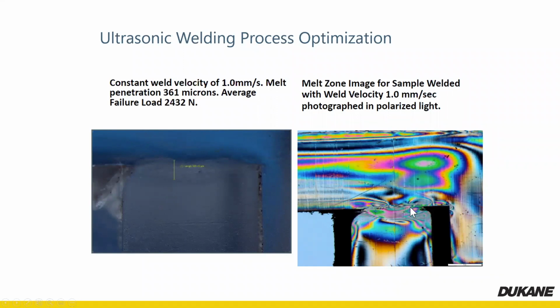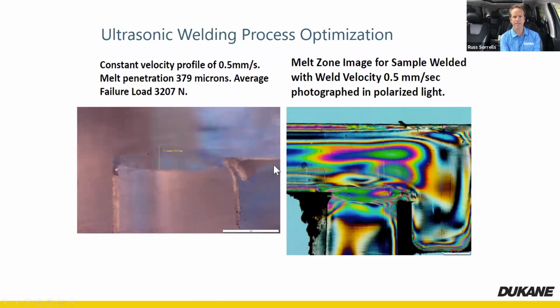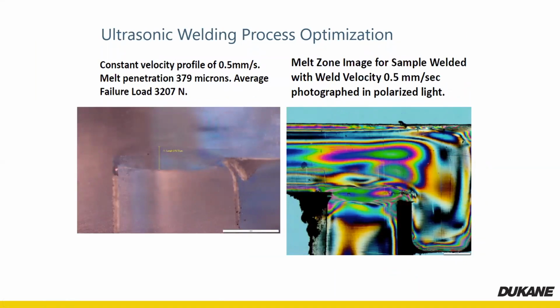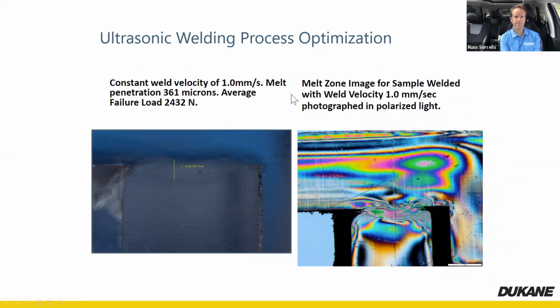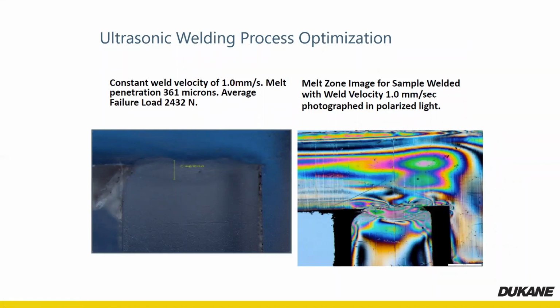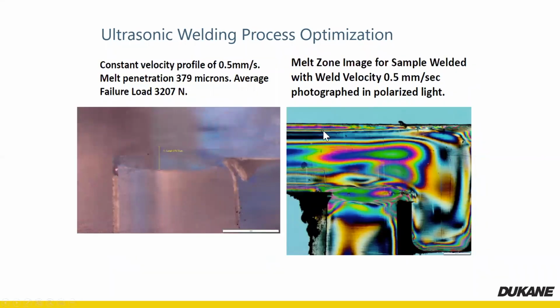And I'm going to go back and forth to these slides so you can see the differences a little bit better. So again, this is 1 millimeter per second constant velocity. So that would represent a pneumatic. Well, no, that still represents servo. Again, that's a constant velocity, and for many applications, this 2,400 Newton pull strength is sufficient, and we don't need to go any further than that, and it works quite well. But there's some instances where we want to try and get more out of this joint than that. And so this was a constant velocity profile.